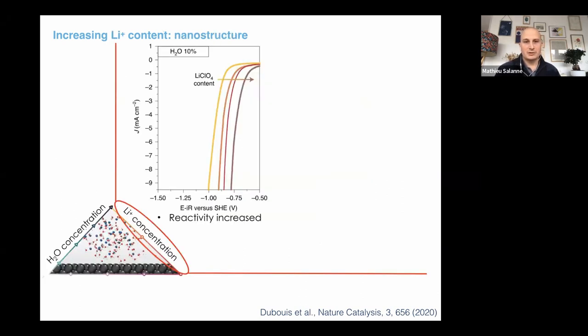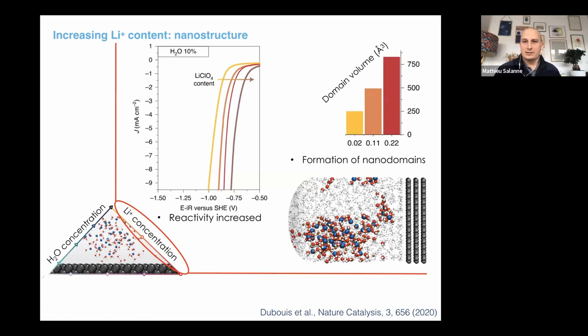Then we increase the amount of salt, either by leaving the amount of water unchanged or by increasing it as well, but the results are quite similar. What we observe is that the reactivity is increased. And so you can see it because the wave is moving to the right here. And in that case, we could not see anything on the local scale, but the most interesting thing we observed is that there is a kind of nanostructuration of the system.